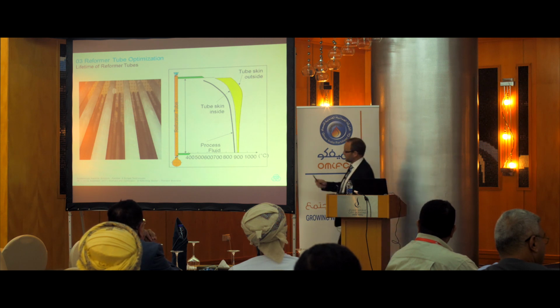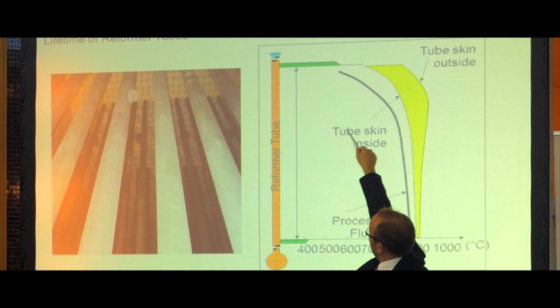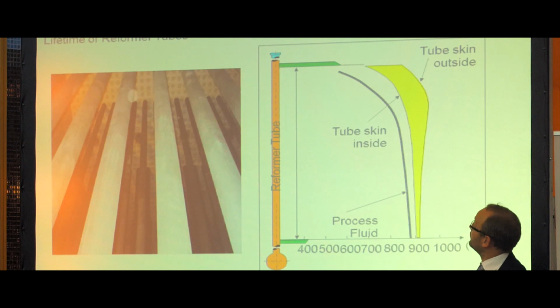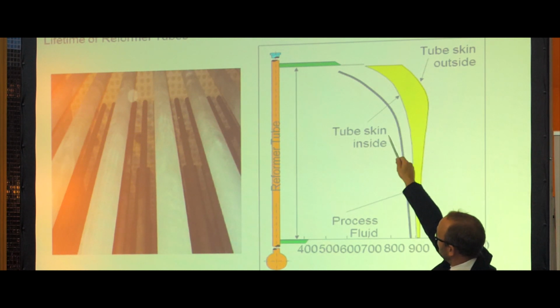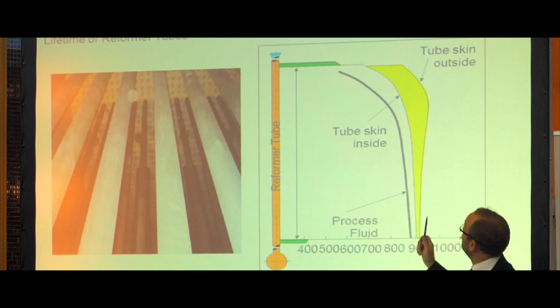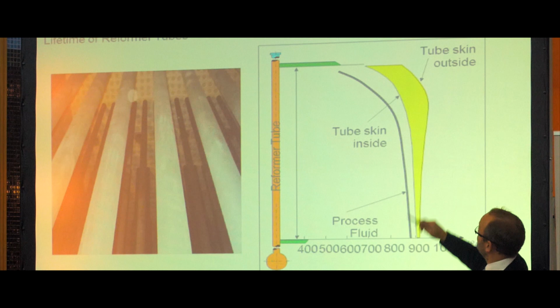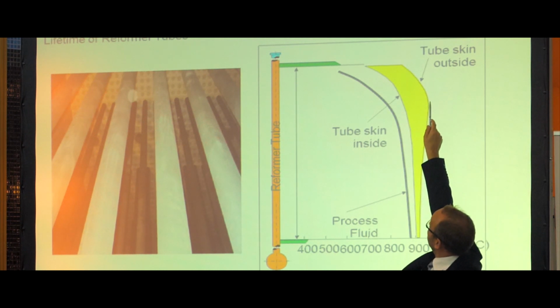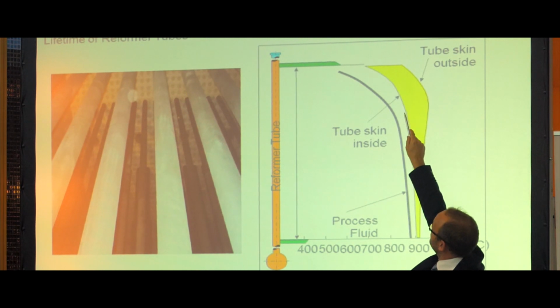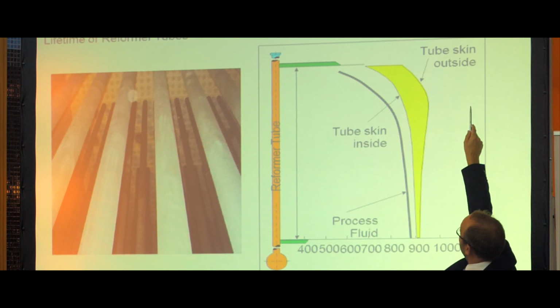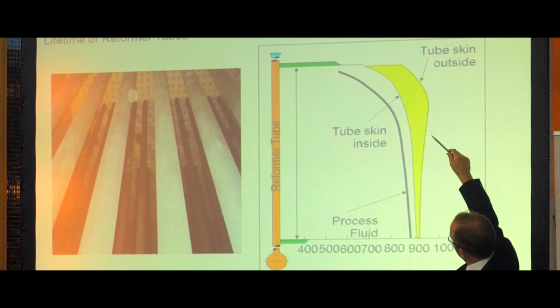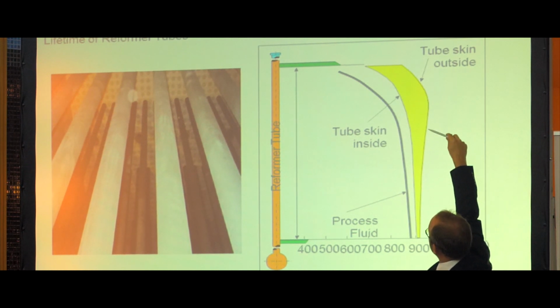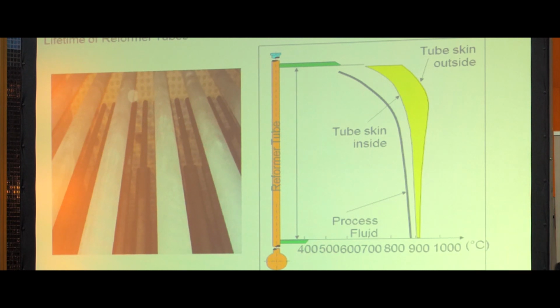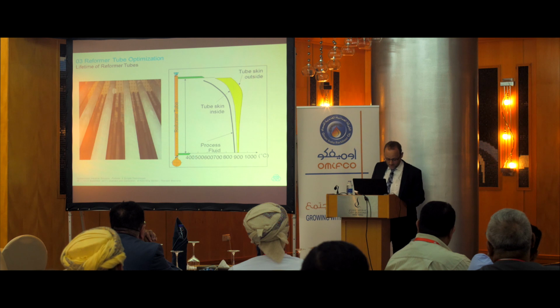Maximum heat release, so it's here in the top area where the burners are installed, you have the maximum heat release, and at the same time, you also have the maximum cooling from the inside because of the endothermic reaction within the tubes. So this yellow area is showing the temperature gradient across the tube section, so outside and inside temperature. And here we have the main part of the chemical reaction inside, and also the main part of the heat, which is released here. So in total, the outside wall temperature is more or less constant over the tube length. With this design, you can ensure a very long lifetime.